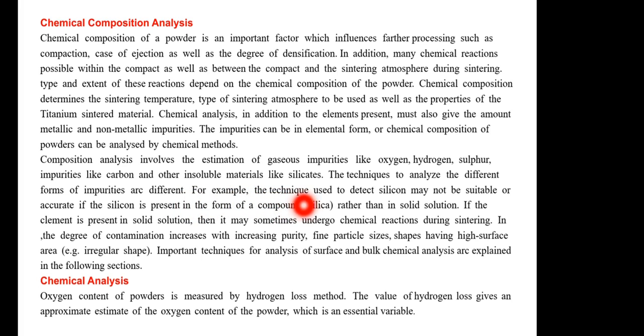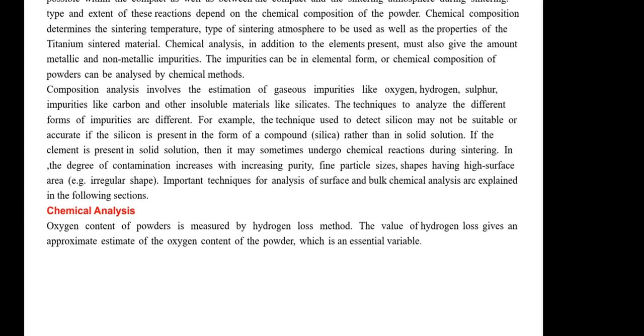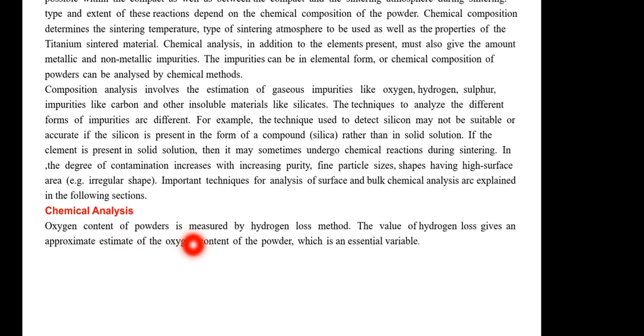For example, the technique used to detect silicon may not be accurate if the silicon is present in the form of compound silica rather than in solid solution. If the element is present in solid solution, then it may sometimes undergo chemical reactions during the sintering. When we carry out the sintering process, at that time that element may undergo different chemical reactions. Oxygen content of the powder is measured by hydrogen loss method. The value of hydrogen loss gives an approximate estimate of the oxygen content of the powder, which is an essential variable.